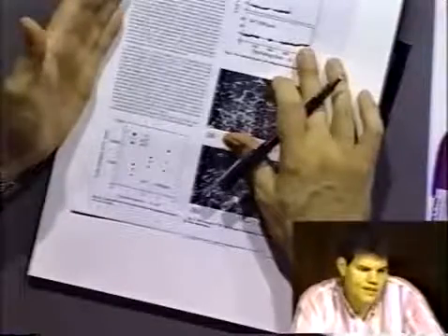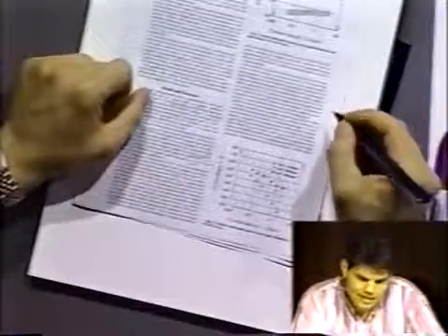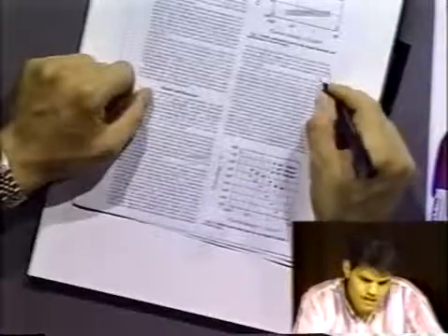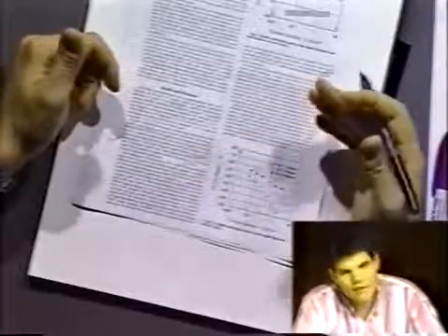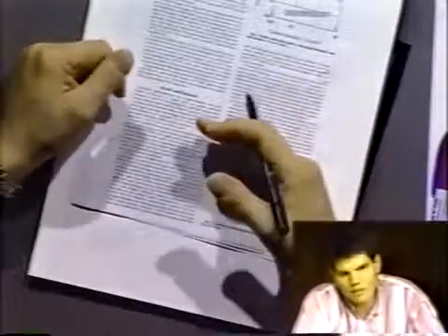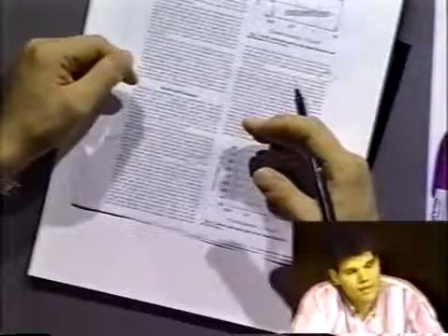What's happening at the end? What's causing it to fail? Why does it fail? Gasification of carbon. And what's that mean? To CO2. Right. It's an oxidation reaction. So in other words, you're basically oxidizing the carbon surface to carbon dioxide. And that's basically a parasitic reaction. You've got the main reaction that you're interested in, which is the oxidation of water, but at the same time you're causing a small amount of material to be oxidized to carbon dioxide.